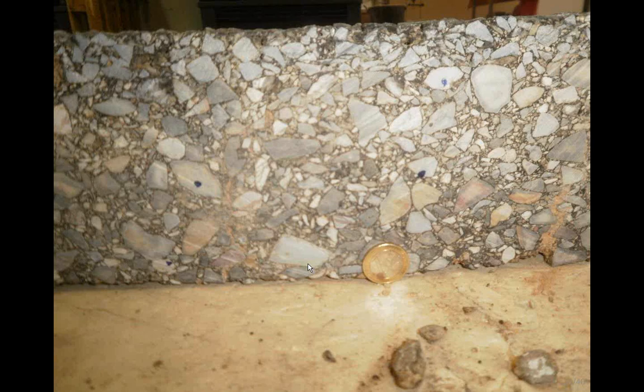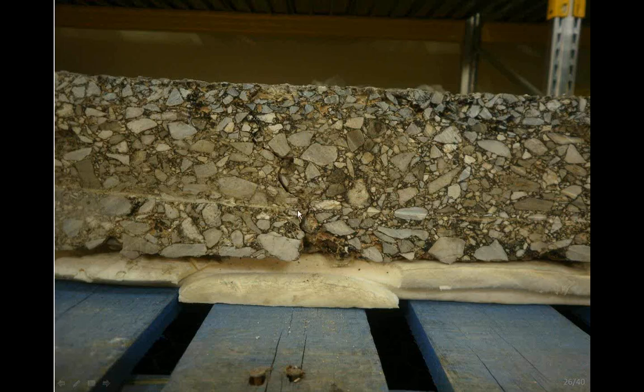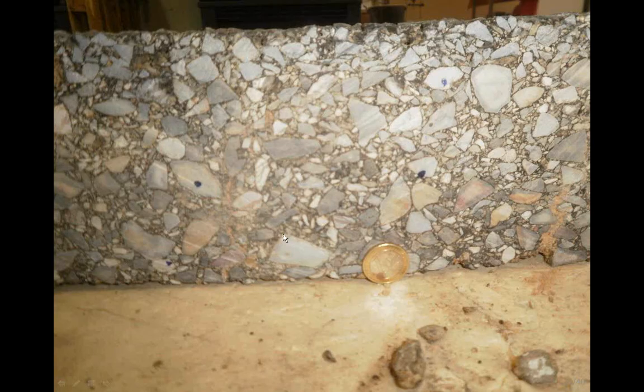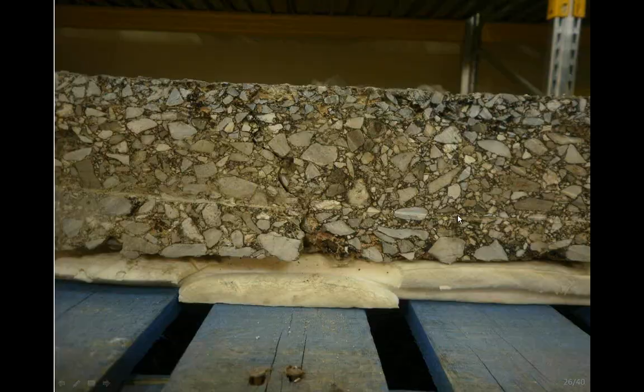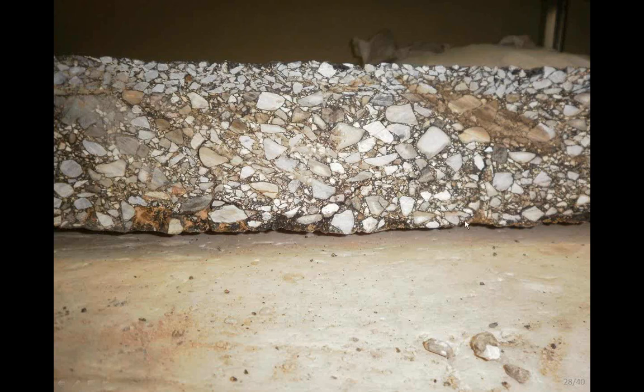Although the thing is that we really didn't know whether or not these cracks were bottom-up or reflective cracks. For example, this one or this one. Is this crack bottom-up or is it reflective cracking? Here you can see again this type of cracking, either bottom-up or reflective. We were not expecting to see reflective cracking here because the modulus of the cement stabilized soil was not very high, so we were not expecting reflective cracking.